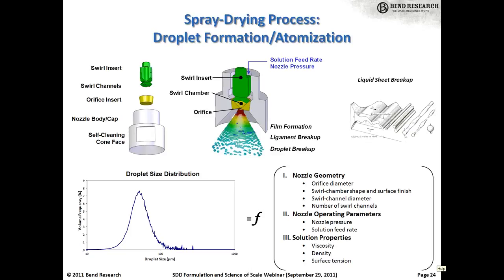For the case of this pressure swirl nozzle, droplet size is related to parameters such as nozzle geometry, so the size and shape of your orifice and swirl chamber. Also related to nozzle operating parameters like your nozzle pressure, your solution feed rate. And then finally, also related to the properties of your spray solution, probably the dominant property that affects droplet size is viscosity.